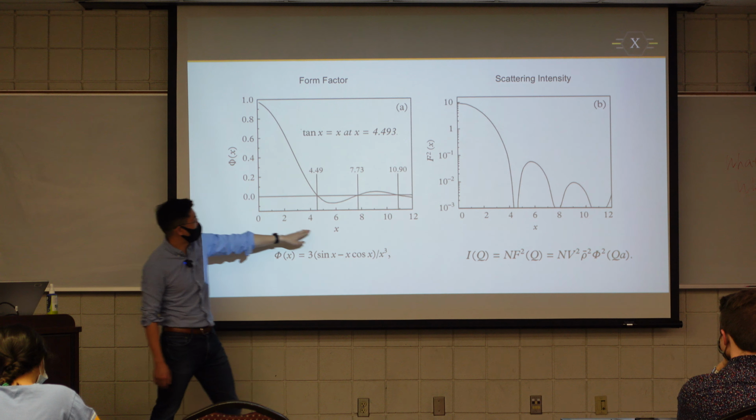In the Guinier region, if my size scale is much bigger than my particle, then I only see the structure and overall shape of my particle. So this is the significance of the Guinier region. Let's go back again. The Guinier region is when you see the intensity plateau. It's a signal that you are measuring the whole overall shape of your individual dilute material.